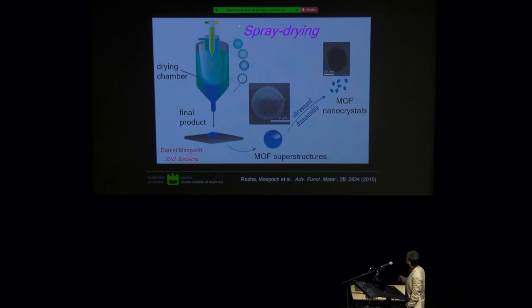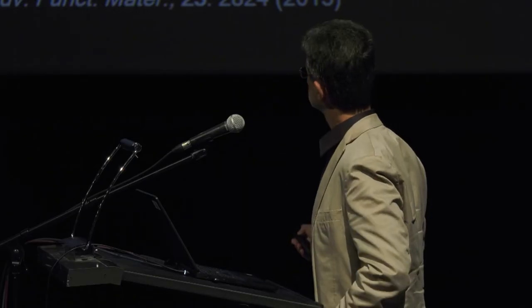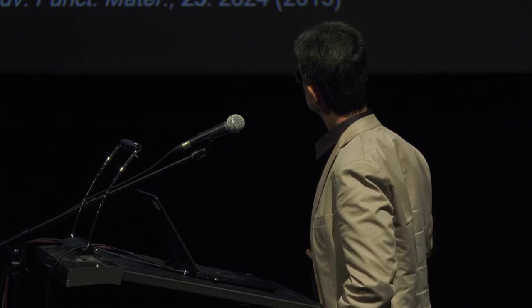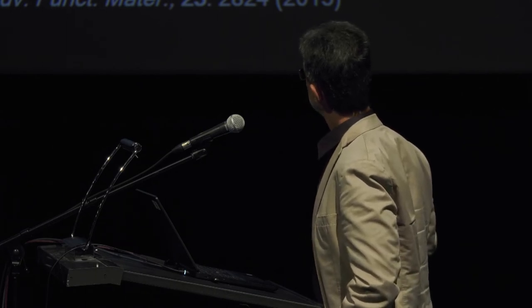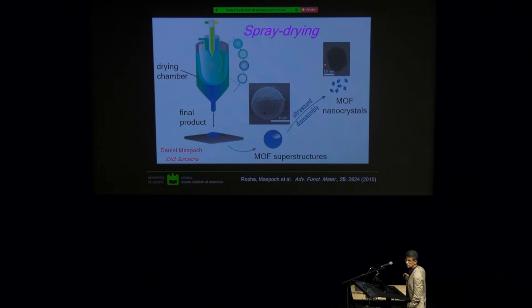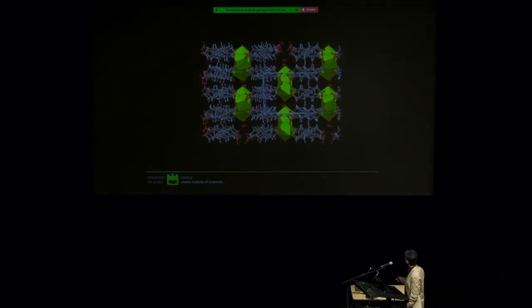Essentially, what you do is you feed reactants from left and right, the linker and the metal, and they come together here, and they spray it from this nozzle into this hot chamber, and the solvent starts evaporating from the center to the periphery. It superconcentrates, eventually crystallizes, and produces these sort of hollow structures. And if you then apply ultrasound, you can get individual nanocrystals. So you can make nanoforms of this material and then use it in thermometry.